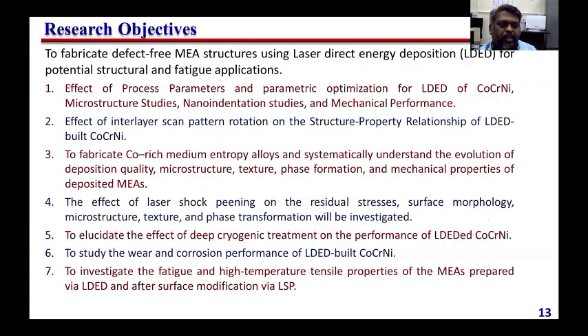For example, this is basically our research objective in this particular alloy. We tried to optimize the process parameters through the LDED process. Basically, we did microstructural and nano indentation study. At the macro level, to understand, we did a microstructural study by SEM, TEM, EBSD, some of the characterization techniques, and to understand the nano level, we also did nano indentation study. Also, we changed some process parameters like interlayer scan rotation. We tried to change the scan rotation and see how the mechanical properties change.